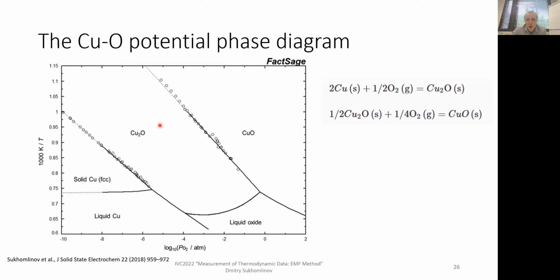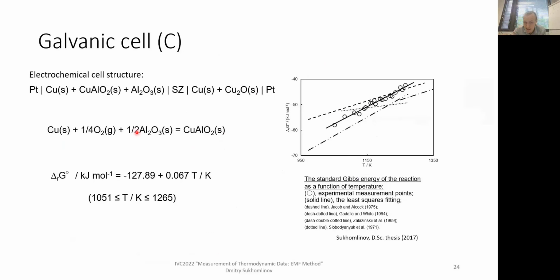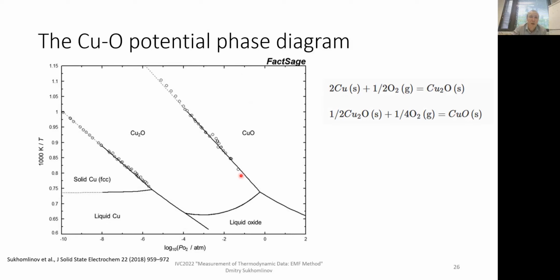Basically, the reason why we conducted these measurements for CuO and Cu2O was just to get reliable oxygen chemical potential for cells C and D, where these were used as reference electrodes. So these data are well known. When we discussed the accuracy of various thermodynamic data, these probably belong to the group which is really well known. And once we found that our measurement is in such good agreement with FactSage calculation, it just gives a lot of credit that what we do is accurate.